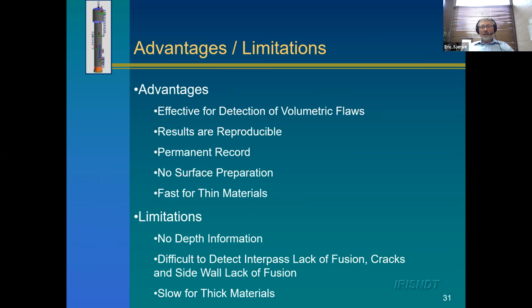The advantages and limitations are almost exactly the opposite of ultrasonics. Ultrasonic inspection is really good at finding linear flaws, but it struggles at volumetric flaws. Radiography is the opposite. It's really good at volumetric flaws, and it can struggle at linear flaws. With UT, the results are not always reproducible. With radiography, they always are because you have a permanent radiograph. With ultrasonic inspection, you have to do surface preparation. With radiography, you never do.